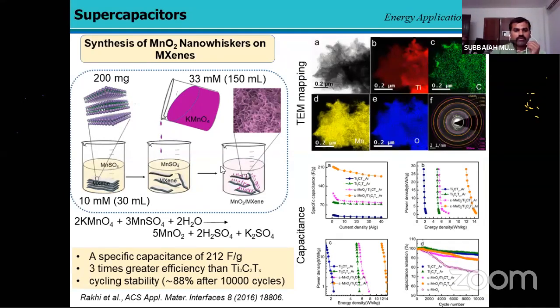Recently, there is a group from India working in South Korea who developed manganese oxide nanowires and MXene material. The appropriate amount of MXene was added to manganese sulfate solution. Then the manganese sulfate solution was oxidized with potassium permanganate. Then most of the manganese oxide was coated, intercalated into the basal plane of the MXene, which was confirmed by XRD as well as TEM images.